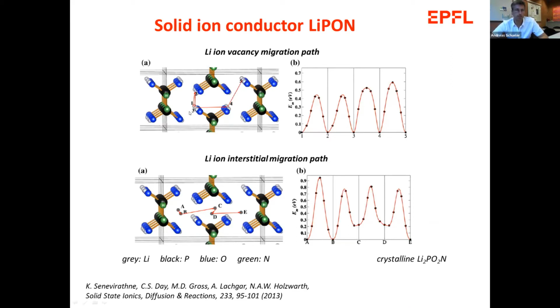So you can see the gray little balls are the lithium ions, and one migration path for the lithium ions is the vacancy migration path. So a lithium ion would migrate and just fill up a site here, a vacancy site, and there would then be an energy barrier involved.